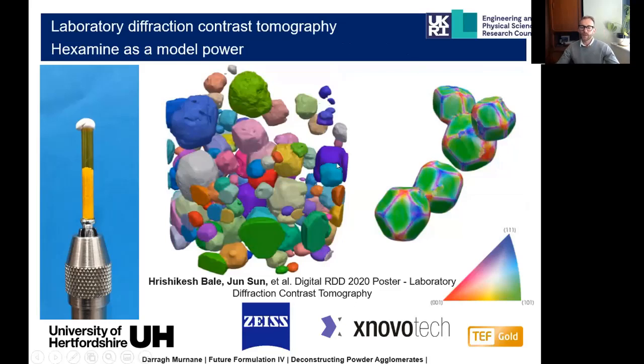And when we do that, we're able to identify individual particles within this powder blend that differ only in their orientation within the powder. So we can see here with this sample of the hexamine, for example, there's a variety of different orientations of these particles which can be identified. And hexamine was a relatively good example to go for, because if we pull out these individual crystals of hexamine, there's only really one family of faces on the hexamine crystal. So it's a reasonable test bed for us to start with. But what we can see is that these particles, the 101 family of crystalline faces, are oriented in a variety of different orientations, and that's how they're colored here.